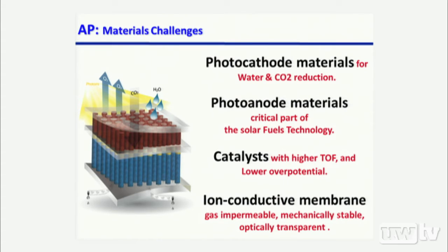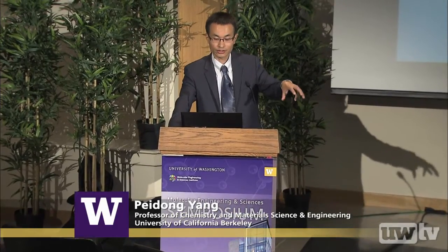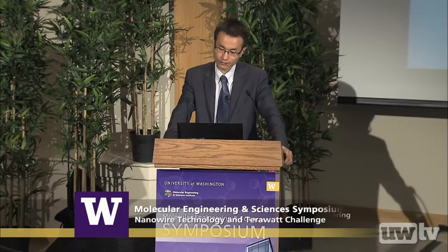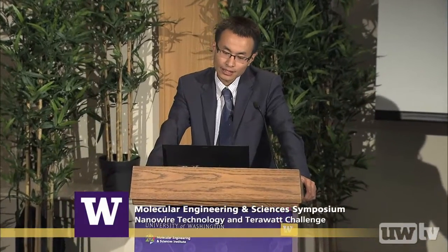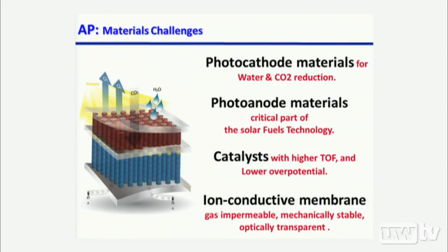And if we look at many of the existing semiconductors, it turns out photoanode material is much, much more challenging. And of course, both semiconductors have to be stable when you immerse the semiconductor in water with one sun irradiation. It has to be photochemically stable. So that's a basic requirement for these high surface area photocathode and photoanode. Then, of course, the semiconductor is taking care of the light absorption. You have to have suitable catalysts to interface with those semiconductors to utilize these carriers. So for water reduction, water oxidation, CO2 reduction, in each of these half reactions, you need to develop catalysts with very high turnover frequency to match the solar flux. And as much as possible, lower overpotential so that the photovoltage you are extracting from the semiconductor is not wasted.